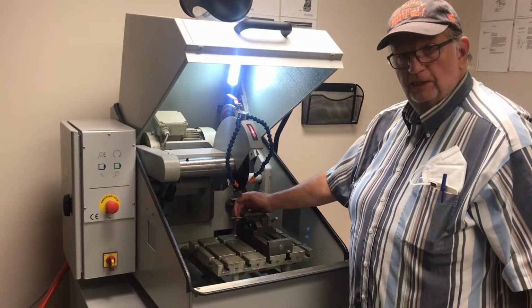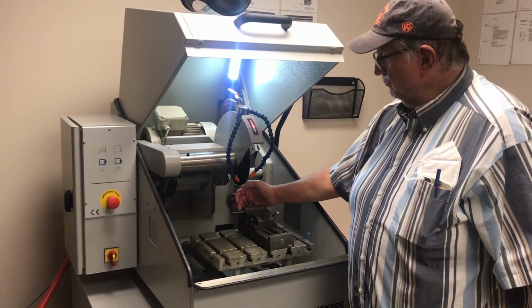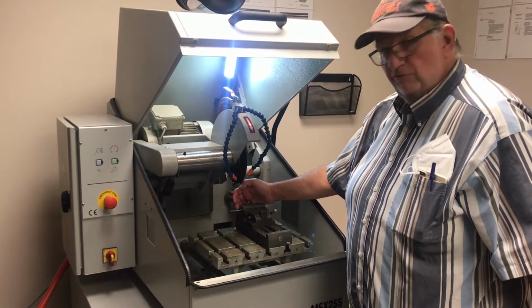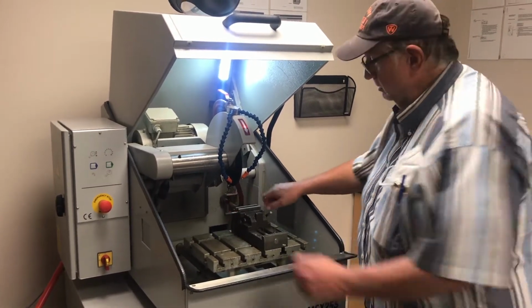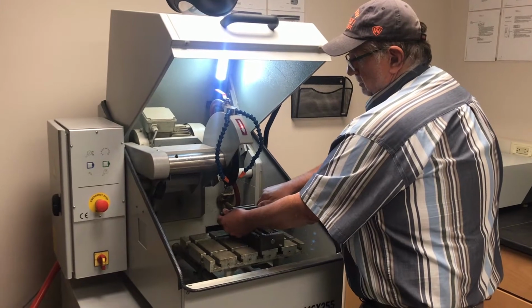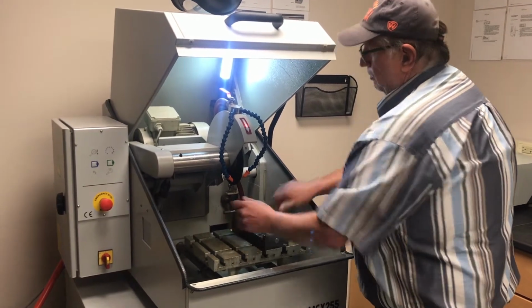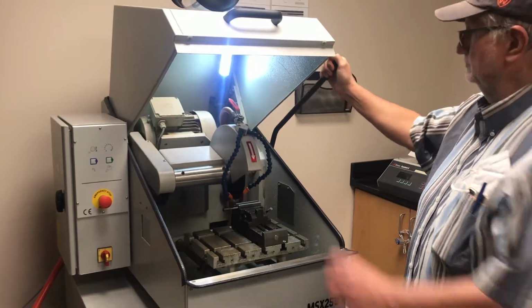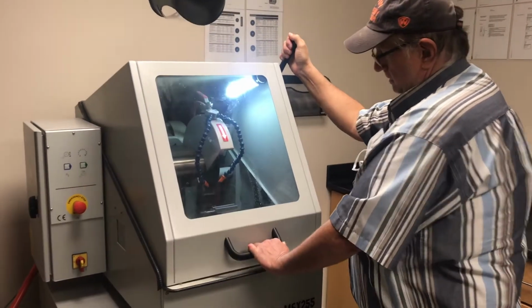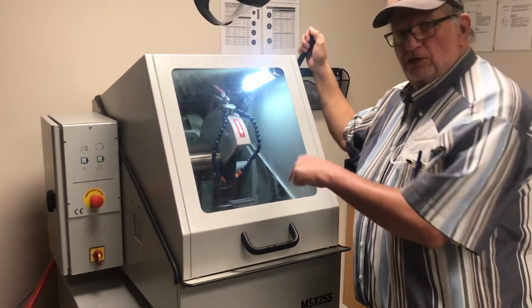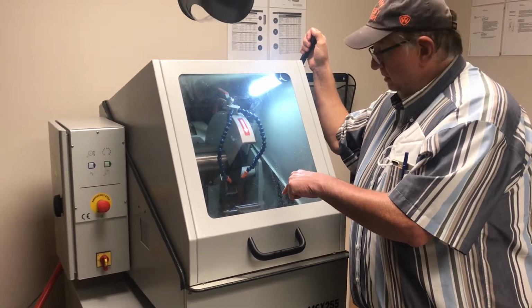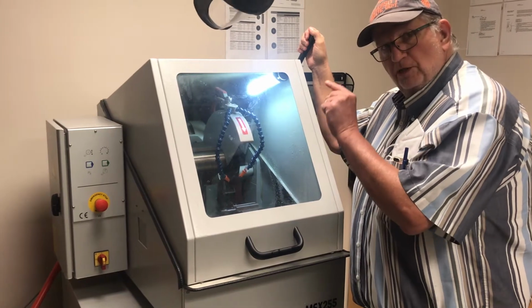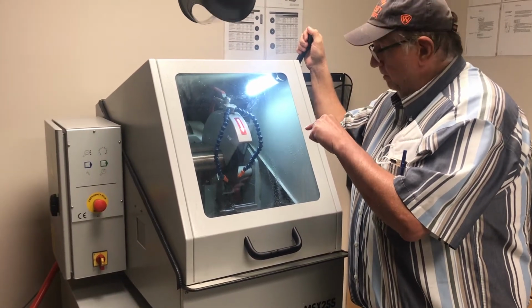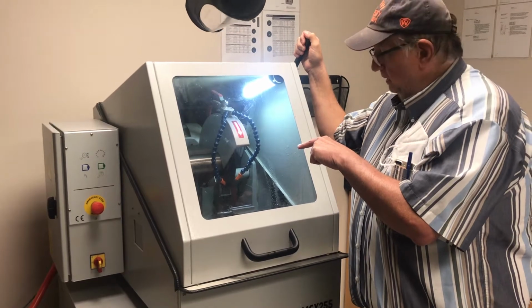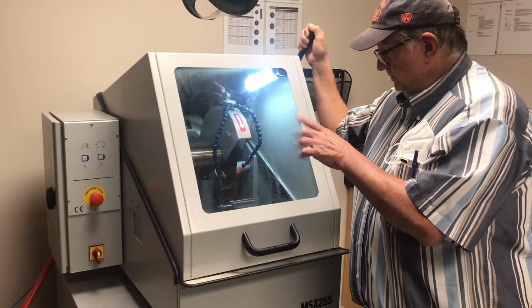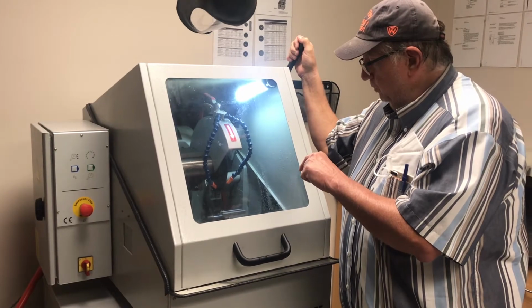You've got to cut off one piece to use for your sample. If you have to cut another one, just reposition the sample by loosening the vise, reclamping, and repeating the process. Okay? When you're done, retrieve your sample from the bottom of the stage. Again, make sure the lubricant is pointing at the blade cutting the sample. Make sure you don't pull too hard. That's pretty much it.